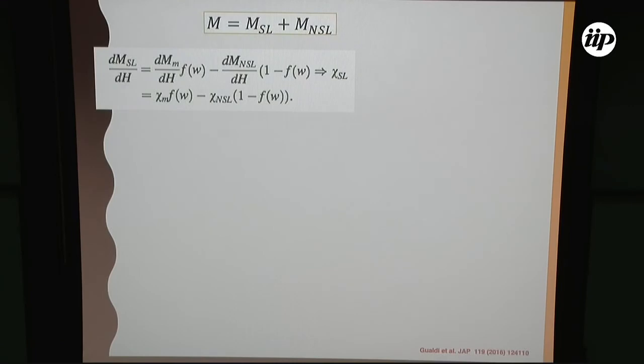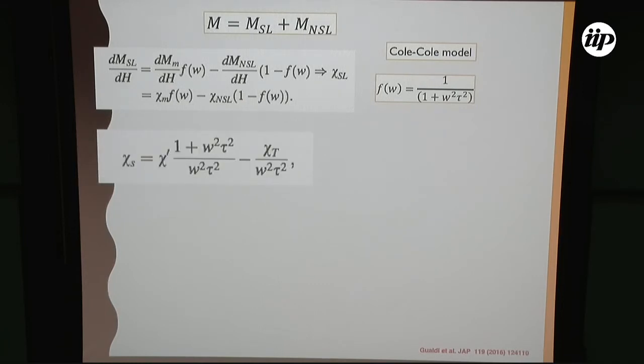So, the magnetization of the ferromagnetic component of this composite can be described, in my proposal, as one part of the magnetization associated with the spin-lattice interaction, and another part with no spin-lattice interaction. The calculation of the effect of the deviation of the magnetization of the spin lattice depends on the frequency, using a Cole-Cole type model. This is a type of spectrum of a relaxation system. It is possible to describe this magnetization, the difference of this susceptibility function, depending on this model. First, I propose for this part the adiabatic process and the isothermal process associated with this susceptibility. So it is a susceptibility associated with spin lattices.